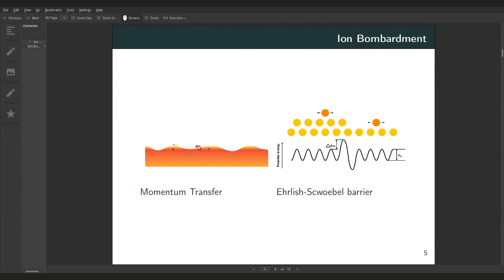So when you have structures on your surface with maybe edges or kinks or bends in them, so a terrace type structure, it's difficult for ions to move across this terrace structure. And so this creates a little bit of a potential barrier. And so it really drives the direction that the atoms on the surface are moving and diffusing because of the structure.